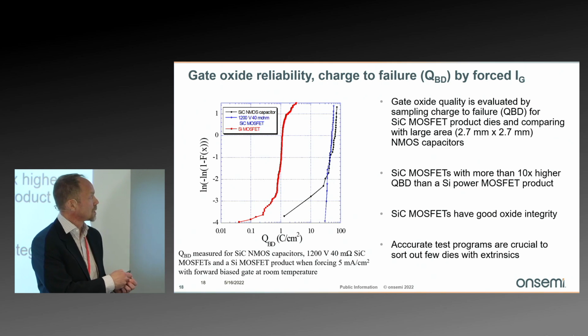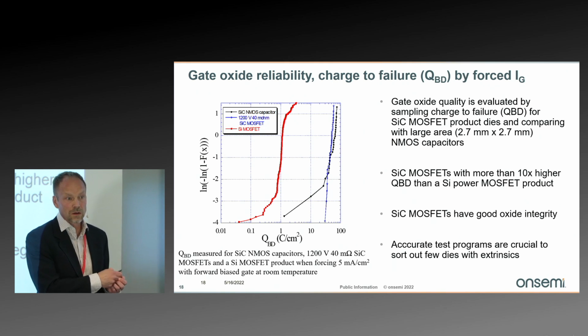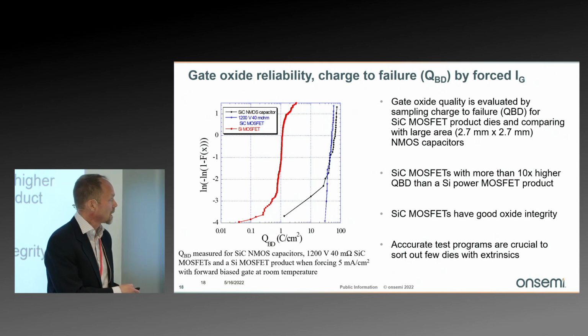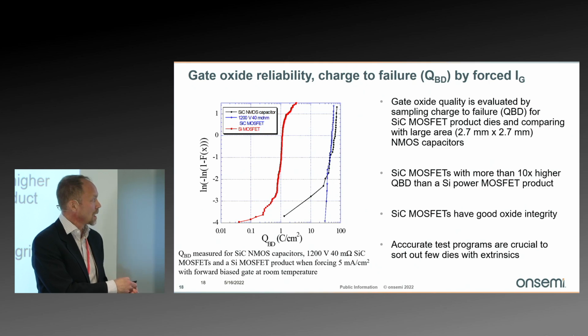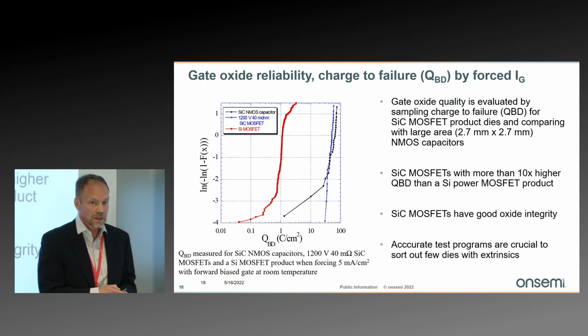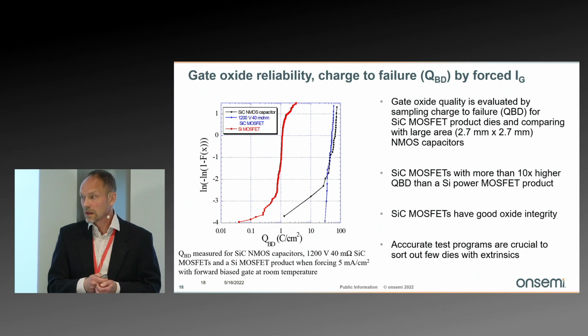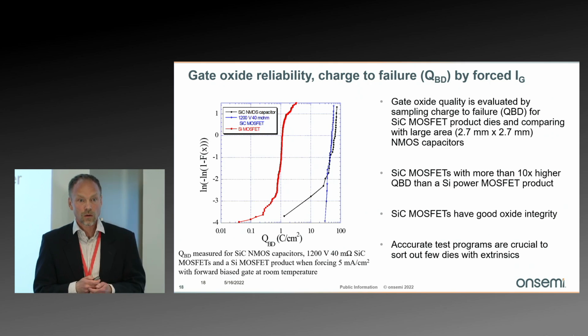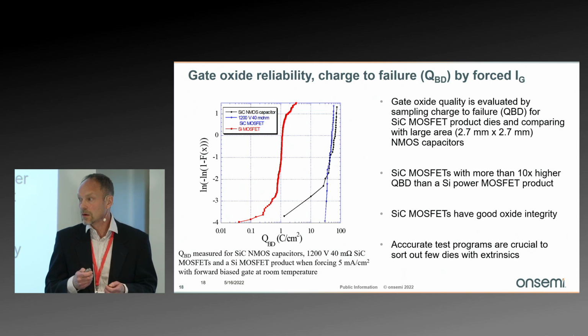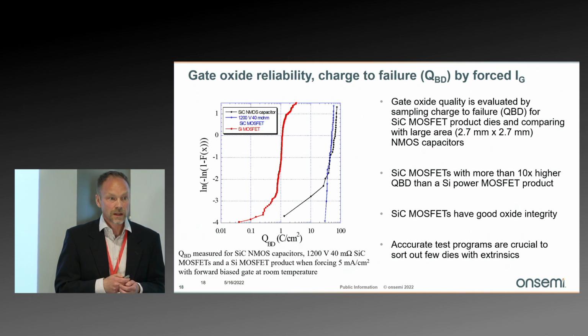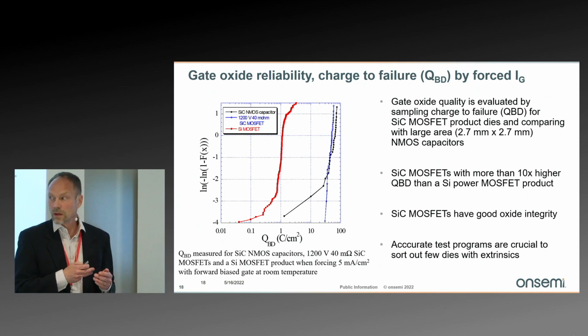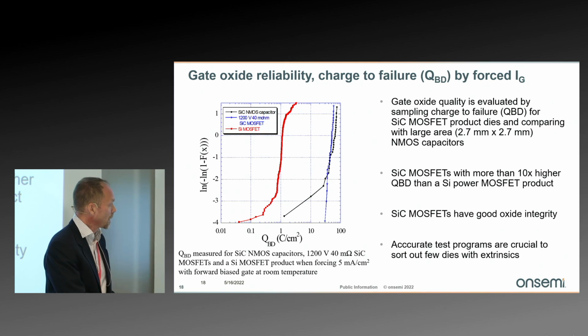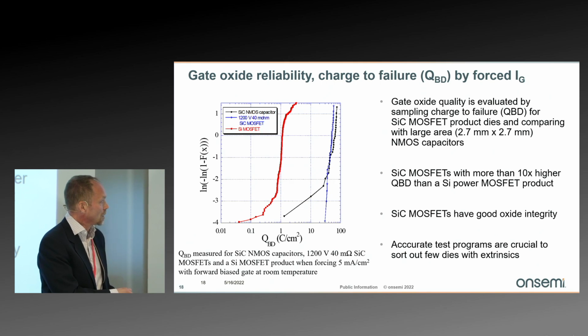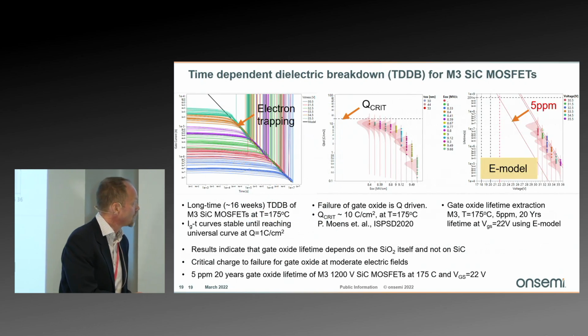And interesting is that we tested silicon MOSFET product manufactured in the same fab, and it's a bit lower in gate charge, which can depend on a little bit different tunneling, but it also has a little bit of a tail. So all in all, we think the gate oxide breakdown in a silicon carbide MOSFET behaves just like on silicon and is controlled by the gate oxide, the silicon dioxide dielectric itself. So this is something we do to monitor the quality, look for potential weak spots in the MOSFET.